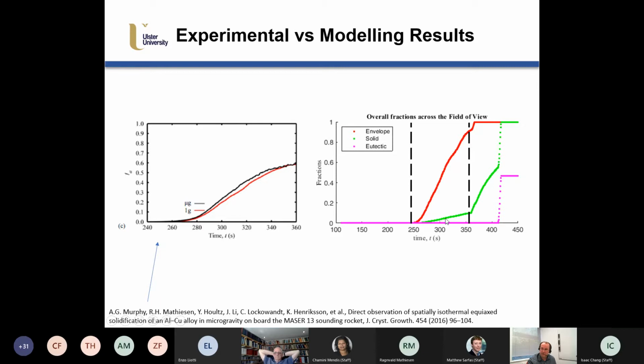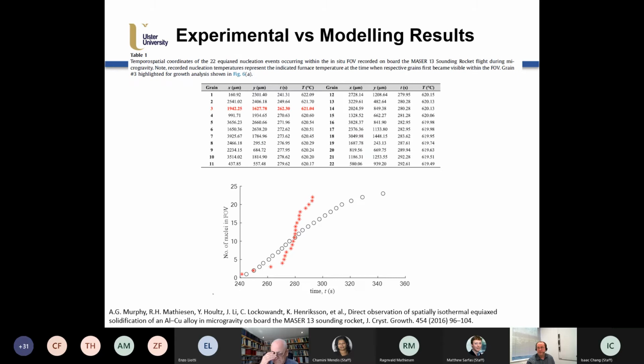And then you see here the solid fraction. So this uptake here in the solid fraction, that is due to a higher cooling rate. So it's a knee point in the cooling rate curve. And then you see this vertical transition here. This is the eutectic coming in. So we've added eutectic to the model as well, which is something we've done through this feasibility study as well. Experimental versus modeling.